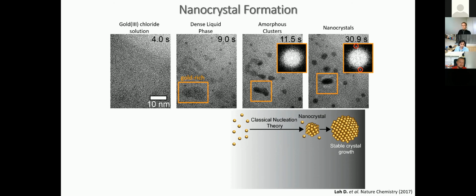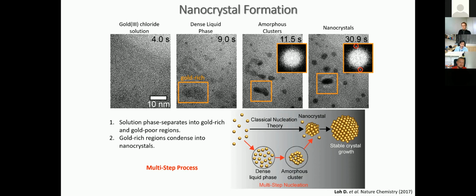Okay, but that's not how one would describe a nucleation process, at least a few decades ago, right? We would use the classical nucleation theory, which states atoms or individual blocks spontaneously come together to form a nucleus of a critical size that can sustain the growth. And if you form this critical size, then your crystal grows, right? Everything happens in a single step. But what we see here is not a single step, it's a multi-step process, right? Because we couldn't see it before, we were missing these other steps that lead to the crystal nucleus formation. So here, by directly monitoring them, you can really identify the missing steps from the previous theories.